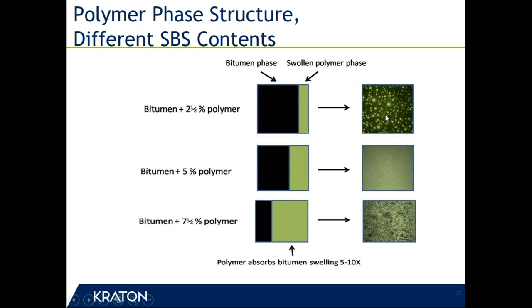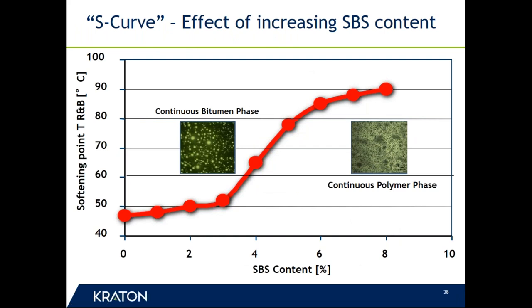So instead of a polymer modified asphalt here, it's an asphalt extended polymer, as you have down here. And if you look at the effect of that on qualities of the asphalt binder, and not every asphalt binder is going to respond exactly the same way, but generally speaking, if you look at a characteristic like softening point, or G star over sine delta, or JNR, or percent recovery, you could see a graphic like this, which we call an S curve, just obviously due to its shape, where you have an area with a rapid change in qualities, and then it levels off up here at the top. When you get up to 7.5% and higher, you wind up having a stable amount of material there in terms of the effect on things such as softening point. And again, you're at that phase where the polymer is completely in control of the response. Since this is a much tougher material and it's an elastic material, you would expect to have better performance from this.